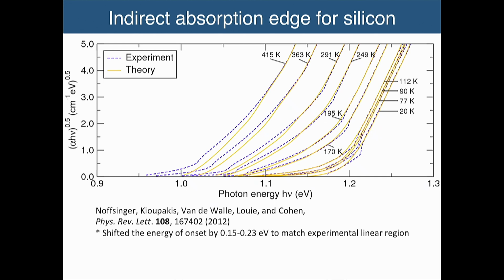And you see that. Let's go first to low temperature. So again, you see a straight line coming from phonon emission, another straight line here coming from phonon absorption. When you're at low temperature, of course, what dominates is the phonon emission. That's why it's much stronger, and phonon absorption is a weak contribution. And the difference in these two onsets is the phonon energy involved in the transition.